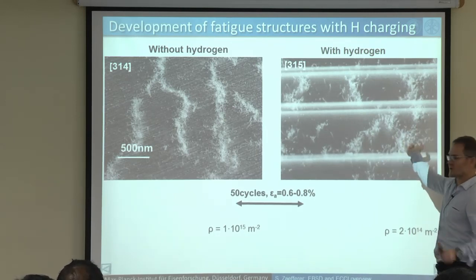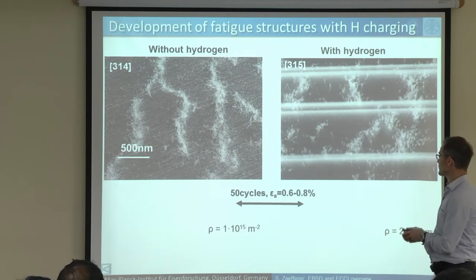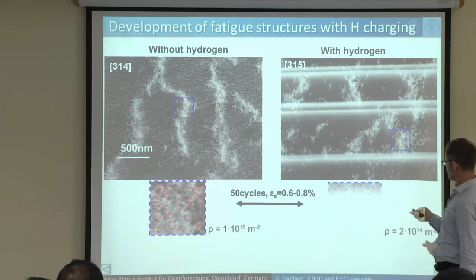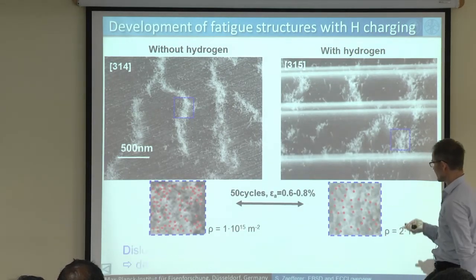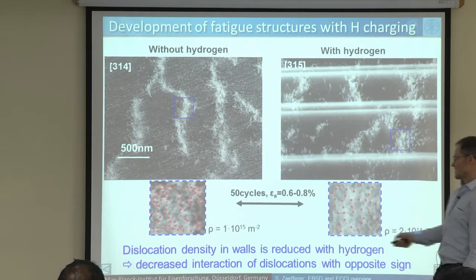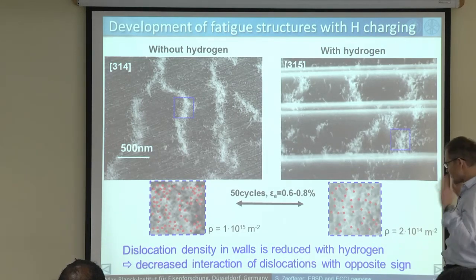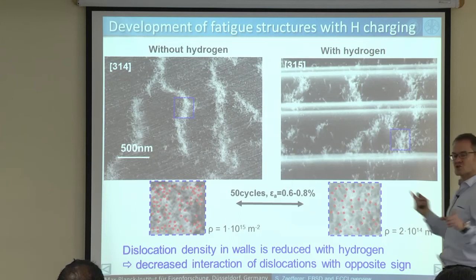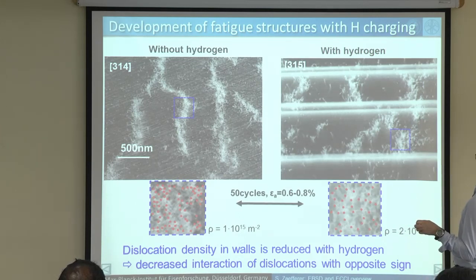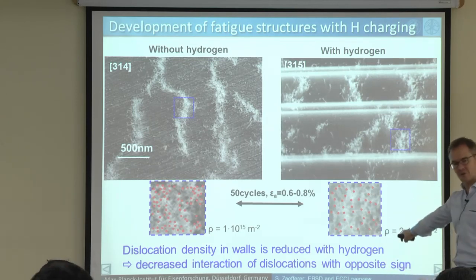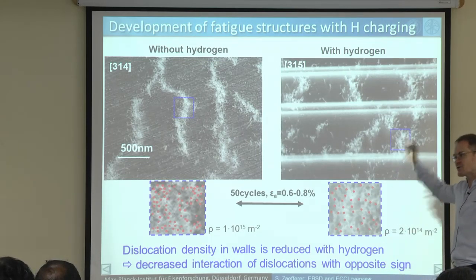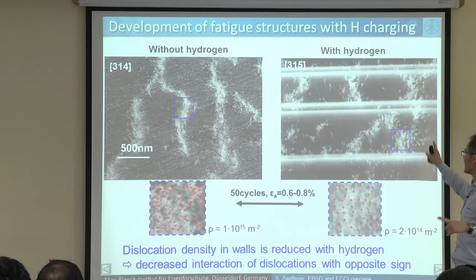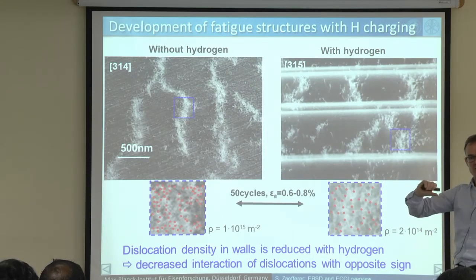And this is not only one observation, we have made many observations, this is always like that. Okay, this is just how we calculate the dislocation densities, and so the dislocation density in the walls is reduced, and that shows, what did it show actually? It's a bit difficult to explain what is exactly written here. I need to go through this step by step to explain you why this is lower, but there is a clear indication that hydrogen is responsible for this low density.